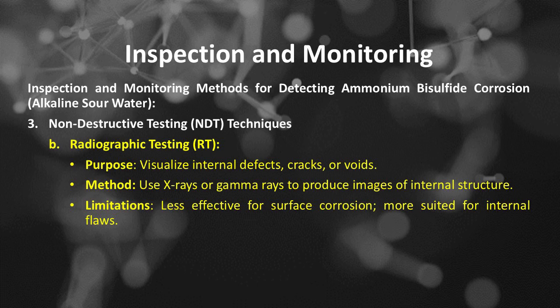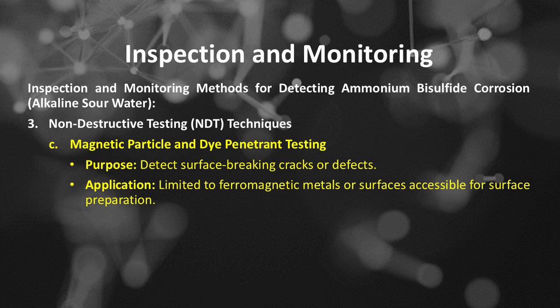NDT. Number B, radiographic testing or RT. It is purposed to visualize internal defects, cracks, or voids. The radiographic testing method uses X-rays or gamma rays to produce images of internal structure. The limitations of radiographic testing: less effective for surface corrosion, more suited for internal flaws. NDT. Number C, magnetic particle and dye penetrant testing. It is purposed to detect surface-breaking cracks or defects. Its application is limited to ferromagnetic metals or surfaces accessible for surface preparation.